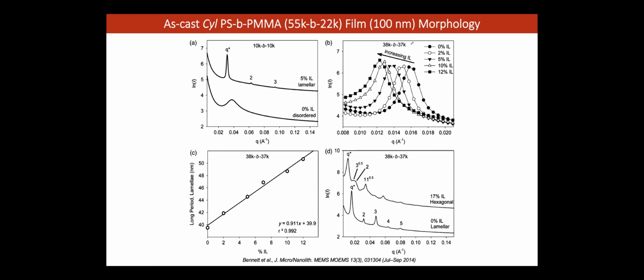And the way he obtained that is, if you look at the log intensity versus Q, with increasing IL concentration up to about 12%, this is now the right-hand corner, you can see a very systematic shift with ionic liquid of the lamellar domain spacing. But at some point, when you add too much ionic liquid, down on the right-hand side, 17%, it actually transitions from lamellae to hexagonal. So it's a whole range of very interesting properties, starting from bringing order into disorder, controlled domain spacing, and then finally, morphological transition.